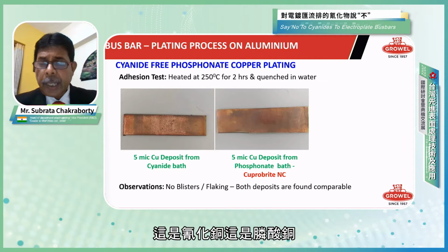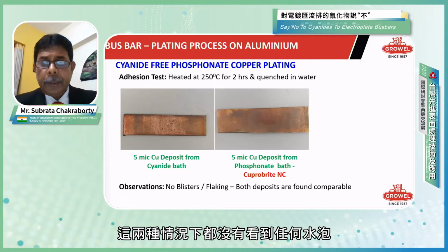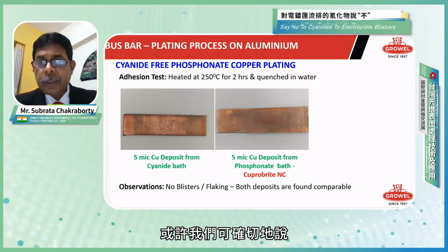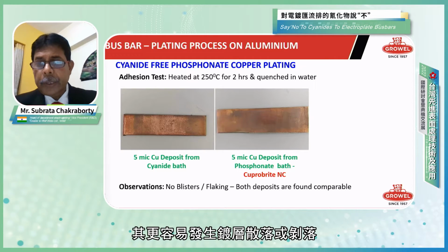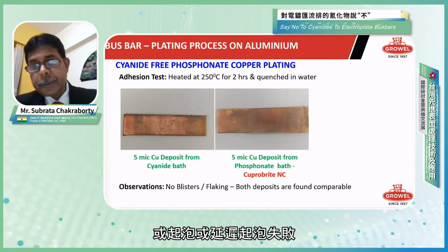This is with the cyanide copper, this is with the phosphonate copper, and we don't see any blister in both cases. So we can say surely that there is no chance of any failure in terms of flake off, peel off, blisters, or delayed blisters.